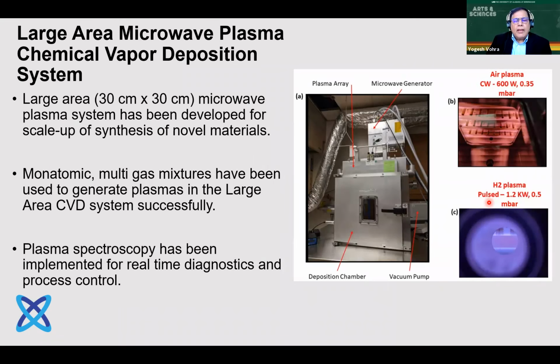So one thing very important is I have pointed out to you several materials which are promising for a variety of applications. So within CPU2AL, we have developed a large area microwave plasma chemical vapor deposition system, which is 30 centimeter by 30 centimeter, and has some very unique plasma array technology. You see these 4 plasma arrays here, and you see these multiple gas inlets for uniform distribution of your reactive gases to be introduced into the chamber.